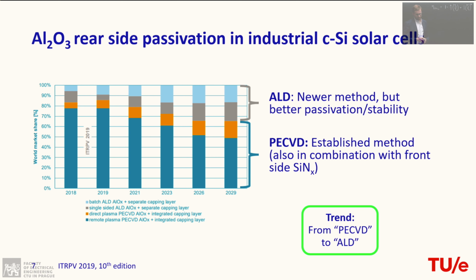Then some more details here about methods, actually, how you make this aluminum oxide. So in the past, people used to use chemical vapor deposition to make this layer. Nowadays, more and more companies are moving towards ALD, atomic layer deposition, because it's known to provide a bit better passivation, and also the uptime of the machinery is higher. So lots of companies are now considering this change, meaning that the market share of ALD aluminum oxide is increasing.